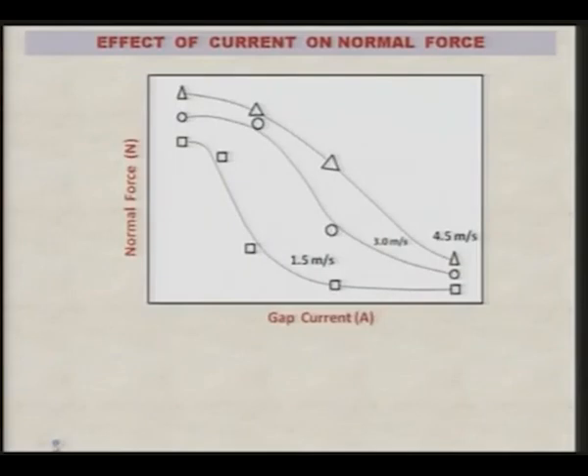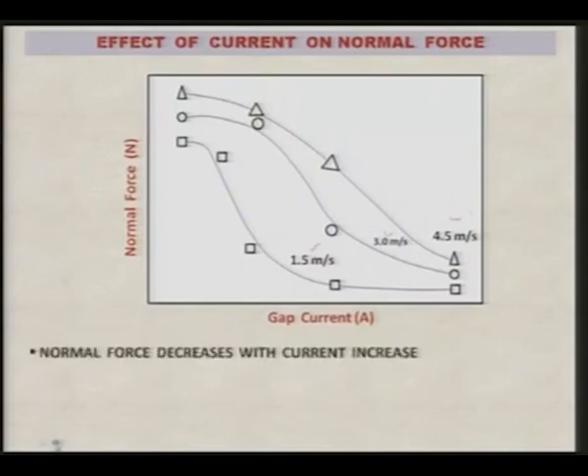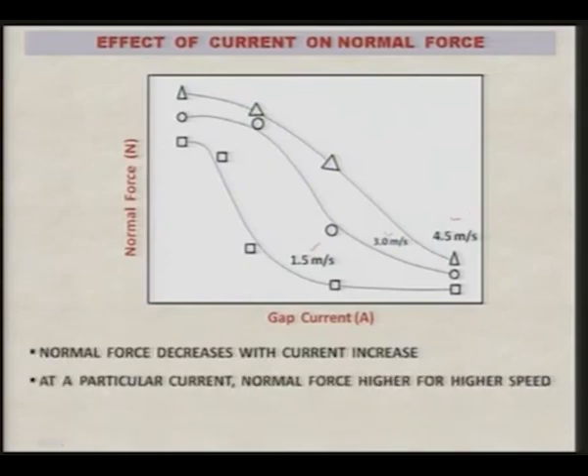Now, let us see the effect of current on normal force. Here this picture shows the effect of gap current, the inter-electrode gap current, on the normal force. Now, as the gap current increases, the normal force is decreasing, not in a linear way, but in a non-linear way, as you can see at different speeds of the table, that is 1.5 meter per second, 3 meter per second and 4.5 meter per second. Normal force decreases with the current increase, and we can see at a particular current the normal force is higher for higher speed. So, if you take a particular current, as the speed increases, the normal force is also increasing.